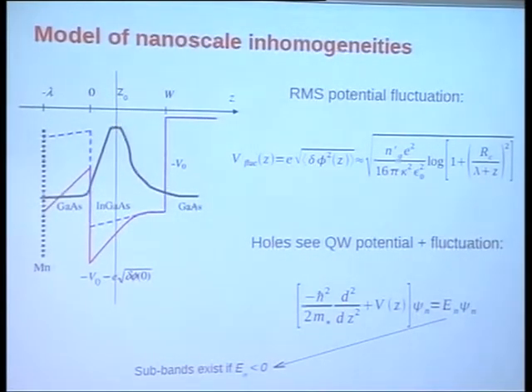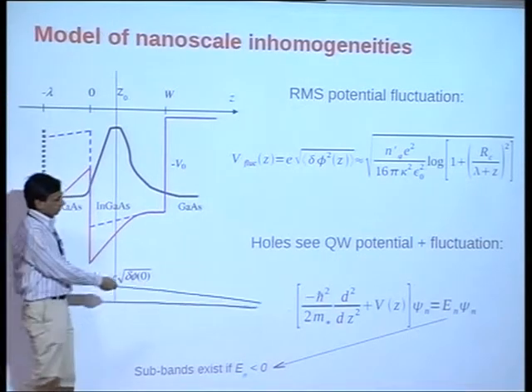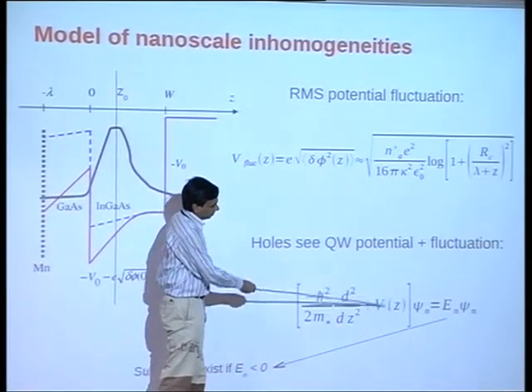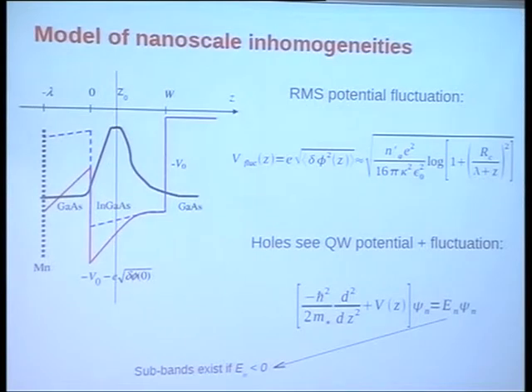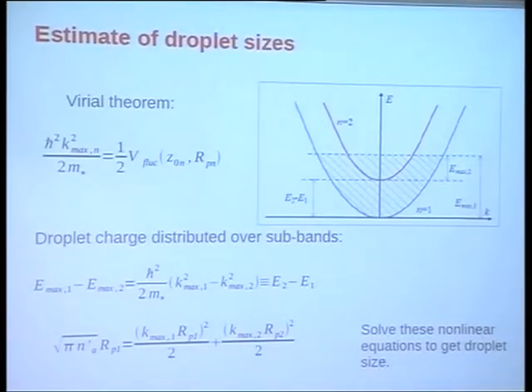So what people typically do here is, because the confinement is strongest in this direction, you need to first have a wave function localized here, otherwise the quantum well will not get populated at all. So you actually need bound states in the transverse directions first. You solve the Schrodinger equation, which includes the potential fluctuations, and you look for negative energy solutions, and that is the subband energy, and you need them negative. Once you have got those, we find that, for the parameters available to us, 2 subbands are populated in some samples, and in one there is just 1 subband populated.